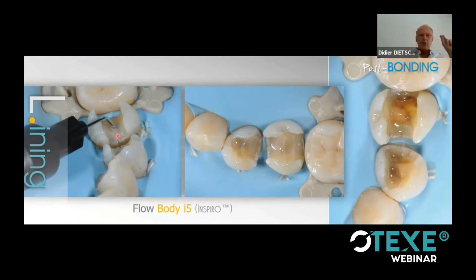When I have a larger volume, I mentioned the fact that we want to create a stress breaking layer. That has been strongly evidence-based in in vivo and in vitro literature, especially in vitro, where it is easier to show that this step might make a difference compared to a technique without the flow. It's very difficult to evidence the impact of that step, for instance, in a clinical study. So we use a thin layer.